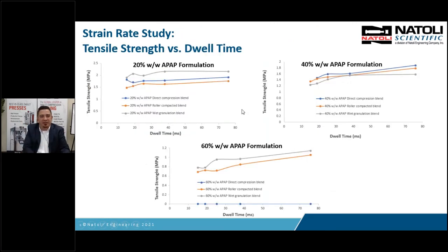This is the same data. Instead of looking at RPM, instead of looking at tangential velocity, we're now looking at the dwell time in milliseconds. So it's the same stuff here, same profile, look and feel, but we're changing the units down here to dwell time. A lot of production machines are probably running in that 12 millisecond dwell time, so they're running in this area right here. But if your machine's running at a lower dwell time, say 5 milliseconds, 6 milliseconds, I can simply just change the head flat on my punch, make it smaller, and I can achieve, theoretically, zero dwell time with no head flat.